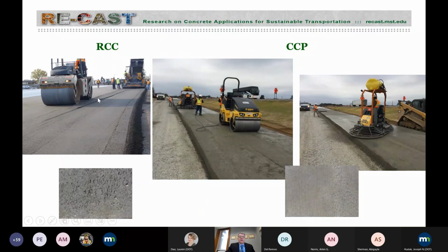So on the left side, you have concrete pavement that is constructed using roller compacted concrete, with heavy vibratory rollers going back and forth to consolidate the pavements. The surface finish is often challenging. You don't have a very good surface finish because of a lack of mortar and the dry consistency of the RCC. The difference with the CCP is that the admixtures bring water to the surface,